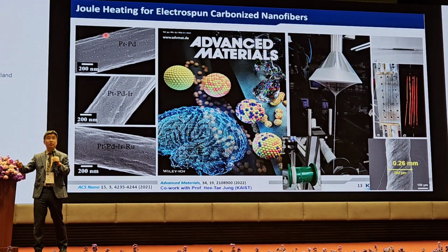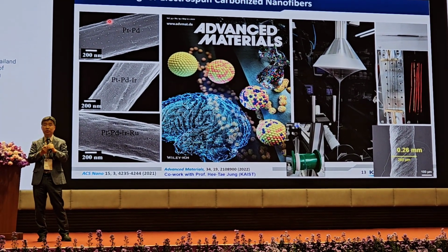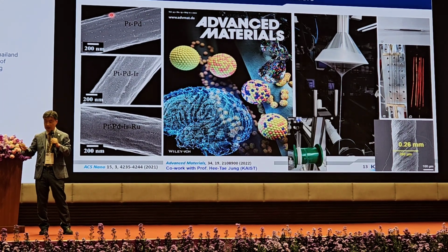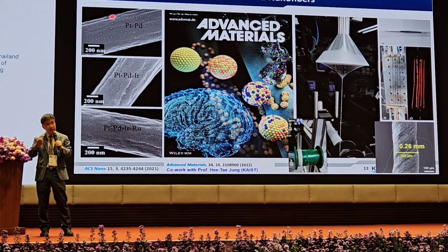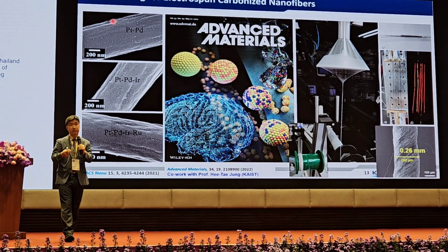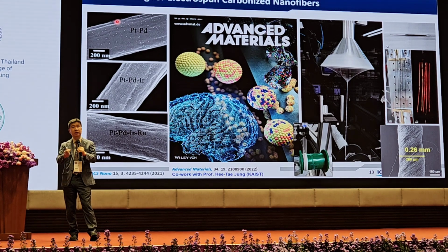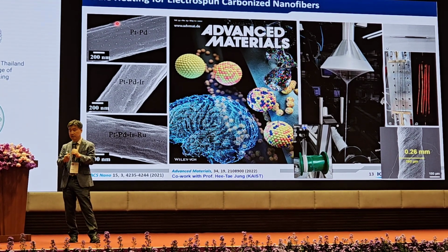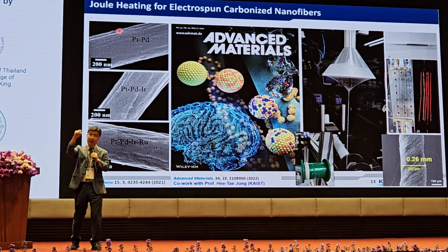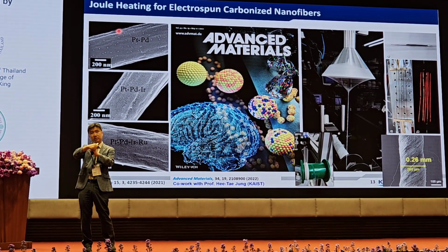Simply by coating 2 precursors, for example, platinum precursors, palladium precursors, mixed precursors, then applying the bias current, you can see platinum, palladium, bimetallic catalyst particles simply synthesized on carbon fibers. 3 precursors, ternary alloy particles, 4 precursors, quaternary alloy particles. These small particles are just attached on the carbon fiber, right?